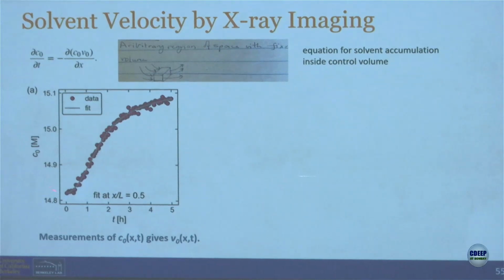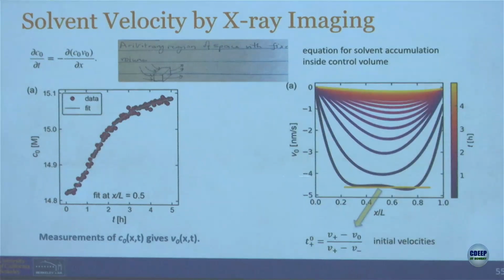This is the salt concentration at one point, changing as a function of time. We fit it to some curve. This gives us dC0/dt, and then we also know what C0 is as a function of t. So from that analysis, we can get the solvent velocity as a function of space. Initially, it's minus 4.5 nanometers per second, and that's the V0 that we need to put into the transference number. With time, this solvent velocity goes down, and it eventually goes to 0, because at steady state, the solvent cannot participate. It can't go anywhere.